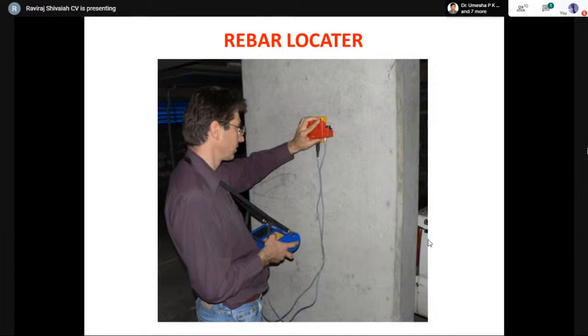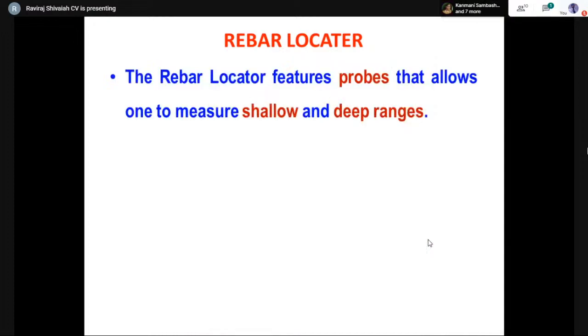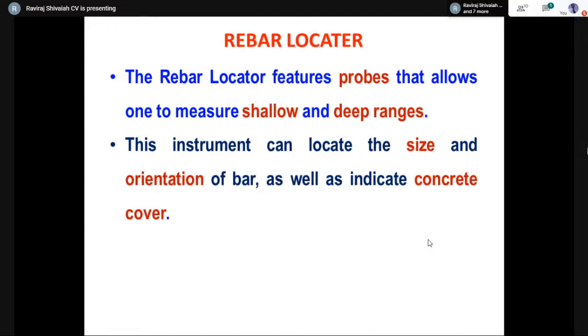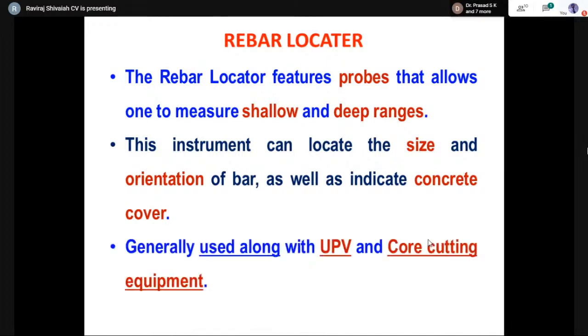You can clearly map it, and you can clearly see that a single person can easily use this particular instrument without any difficulty, right? So generally, the instrument can have two different types of probes, but you can attach only one probe at a time, either a shallow probe or a deep probe, correct? Shallow probe is less sensitive and works only for small distances; deep probe is for relatively large distances, correct? And this can give you the size, orientation of the bar, and also the clear cover.